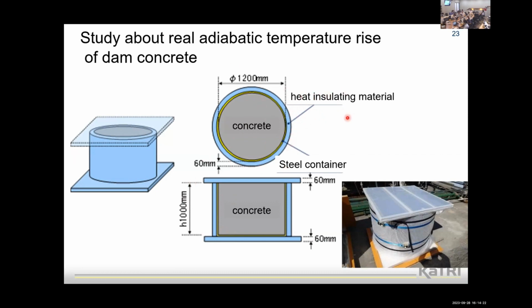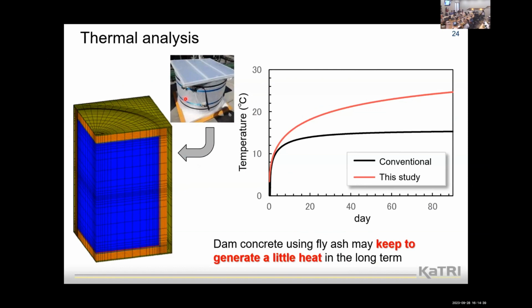So we try to study the real adiabatic temperature rise of dam concrete using this equipment: the heating insulation materials, the steel container, and the concrete. We put the concrete in the steel and measure the temperature inside the concrete, and then we simulate this equipment in thermal analysis. With this we get the adiabatic temperature rise of fly ash concrete. The black line is the conventional data, and the red line is the data we got in this study. Some concrete using fly ash may keep generating a little heat in the long term.